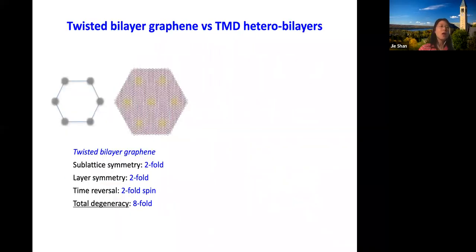Okay, so now I would just like to give you a quick comparison between twisted bilayer graphene and the TMD heterobilayer. So in twisted bilayer graphene, we have sublattice symmetry, a two-fold degeneracy, layer symmetry, that's another two-fold, and we also have spin degeneracy. So altogether, each band is 8-fold degenerate.